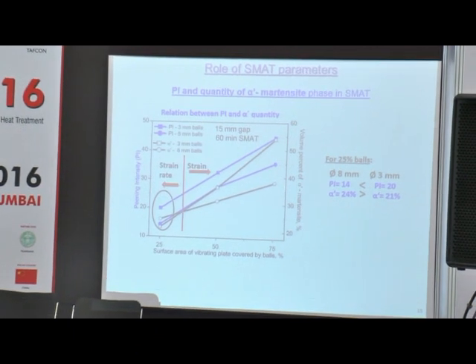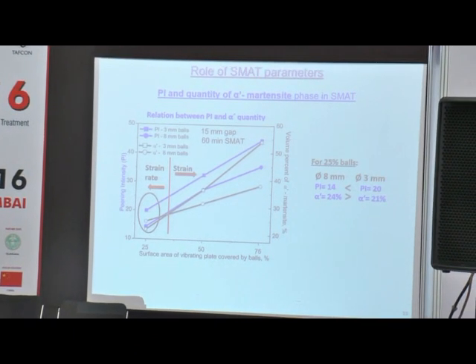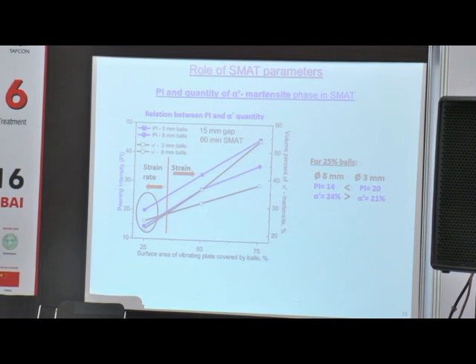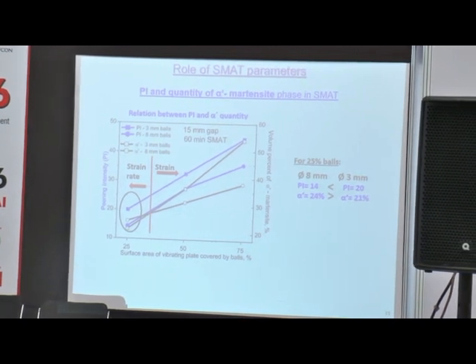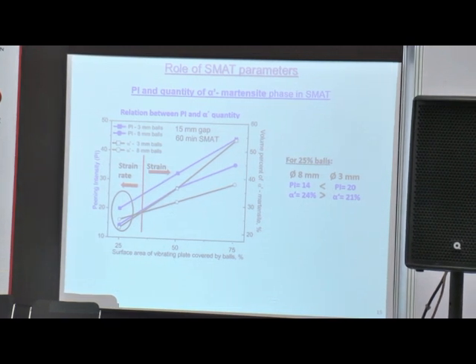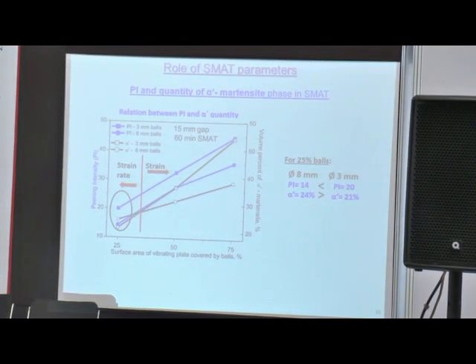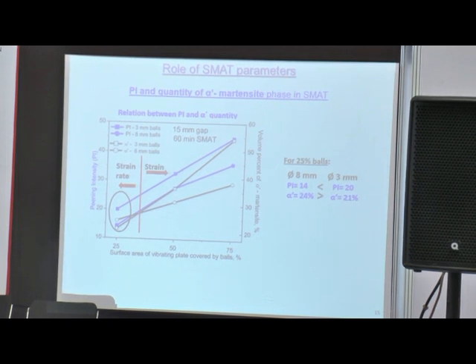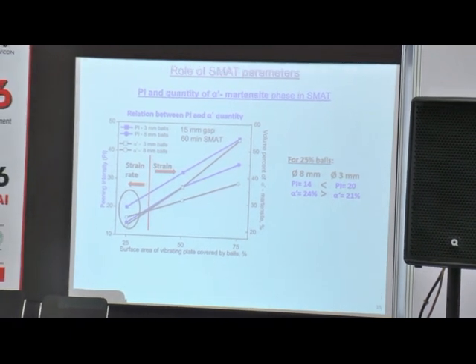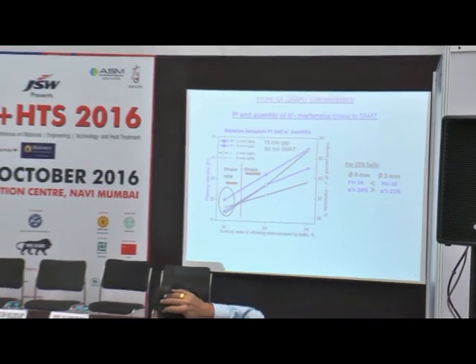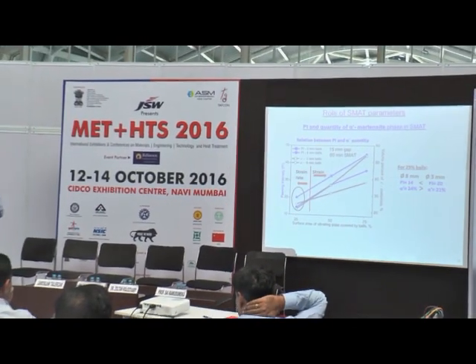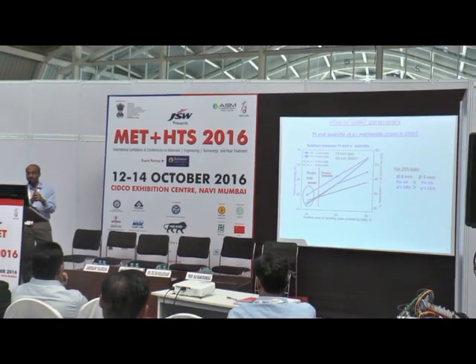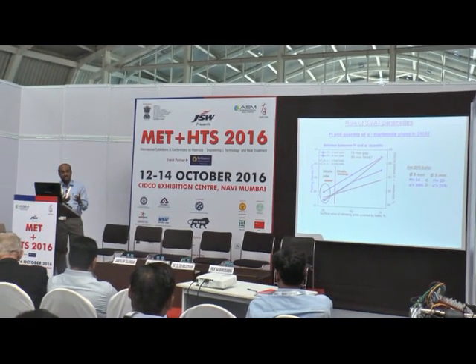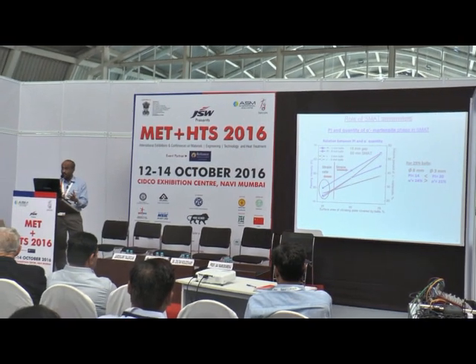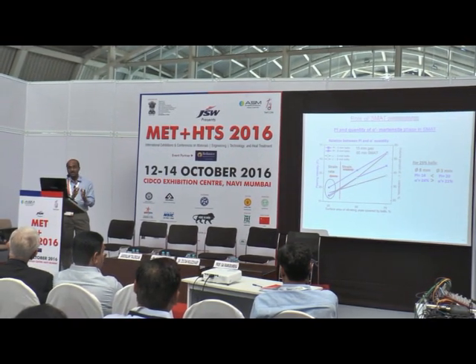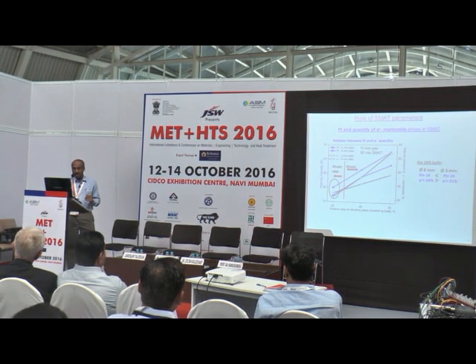However, at the lower percentage of ball, you see the reverse trend. What does that mean? Even though my pinning intensity is more for the case of the 3 mm diameter ball, still the martensite quantity is lower. Why is that so? Because there is another term which comes into the picture, that is the strain rate. You have a higher strain rate when only a small quantity of the space in the chamber is occupied by the ball. So you have a very large velocity and less collision between the balls, so you have a high strain rate. The higher the strain rate, you have adiabatic heating, and because of that adiabatic heating, you have a lower percentage of martensite quantity. Anyway, these are all related to the martensite quantity.